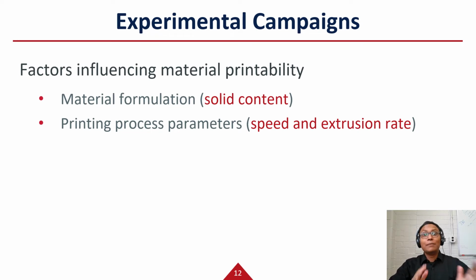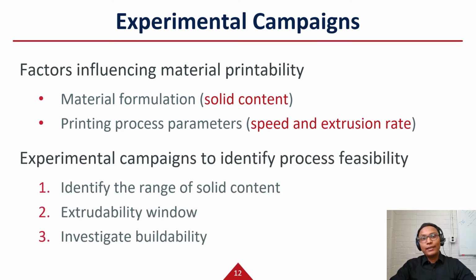The intuition is that the material formulation has some influence on the printability because the paste rheology depends on the hydrogel to regolith ratio. Therefore, we varied the amount of regolith in the material mixture and conducted experiments for different solid contents. The literature also suggests that the printing parameters could impact the printability. Primarily, we are only considering the printing speed and extrusion rate. We conducted a preliminary investigation to identify the workable range of solid contents, that is the amount of regolith in the material mix. Then, we used an experimental design approach to find how the printing parameters and their interactions affect the printability of the material.